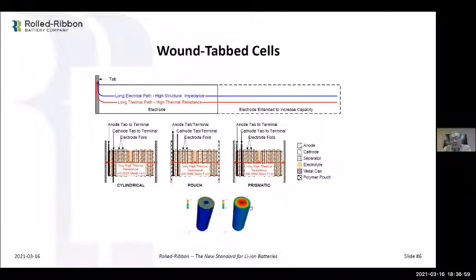In here, the tab is on the outside, so it's cooler. It's closer to where the heat escapes. But this travels a longer path, so the heat becomes pent up and built up. And when you have gradients in a cell, you have uneven wear. The cell will wear out faster when you do that.